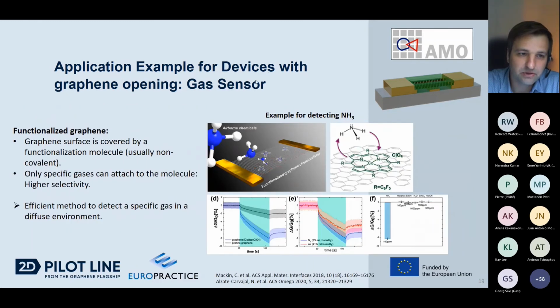An example for having these devices with an opening on top of the graphene layer is shown here. This allows you to functionalize the graphene, for example, with a molecule which is sensitive to NH3. And in this way, you have a conductance change, very selective for this special molecule. And so you can realize a gas sensor with this device.